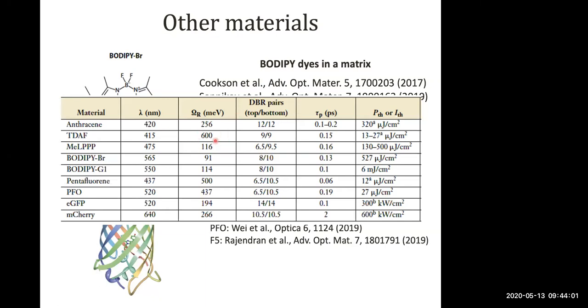But actually, if you do a calculation of the anticipated molecular structure of the amorphous film, you see these molecules are very twisted, and the dipoles are well separated. And in fact, if you look at the solution properties and the thin film properties, you see that they're very similar. So this tells you that in the thin film, aggregation and exciton-exciton interaction doesn't play an important role. So these are acting in almost all of the cases, I would say, except for PFO and anthracene, as isolated chromophores.